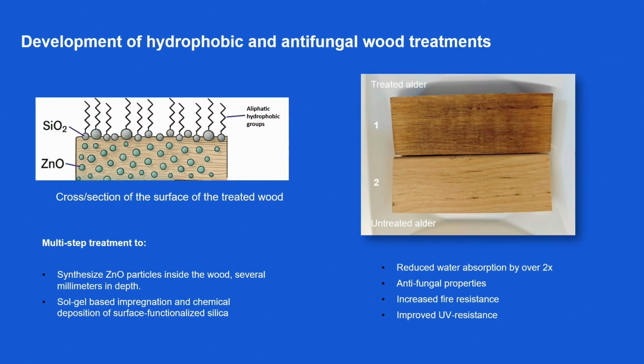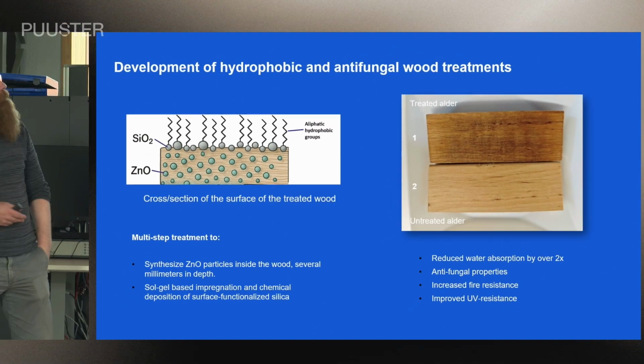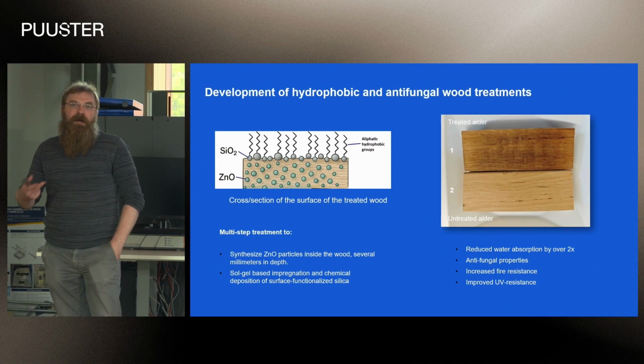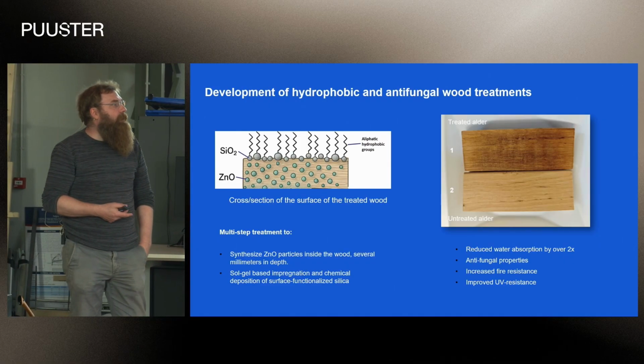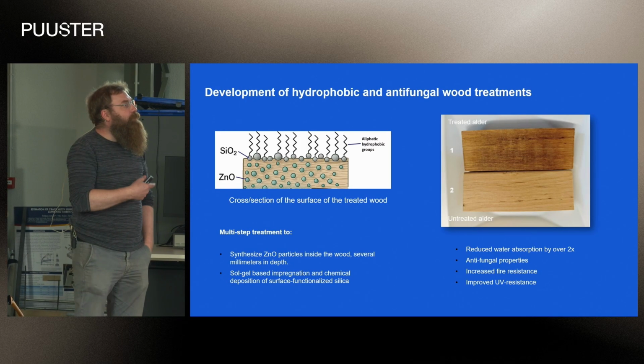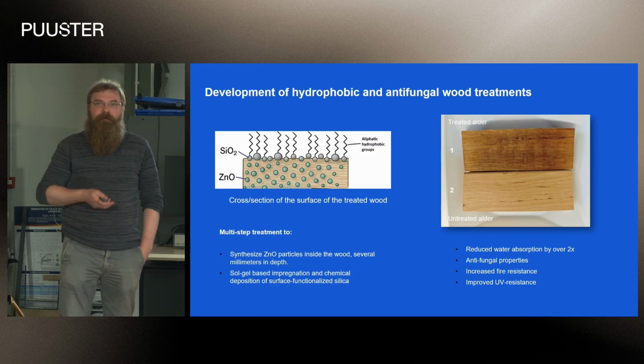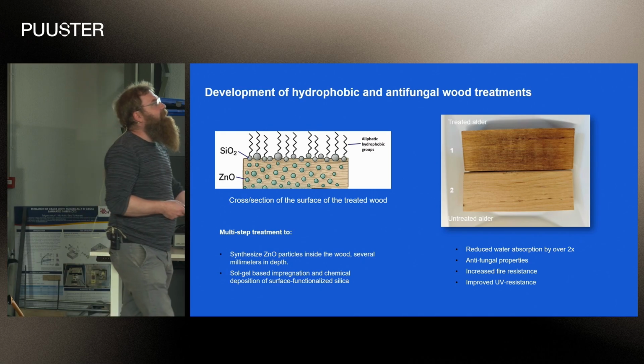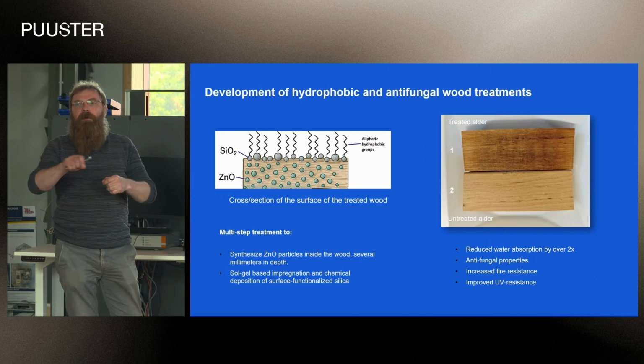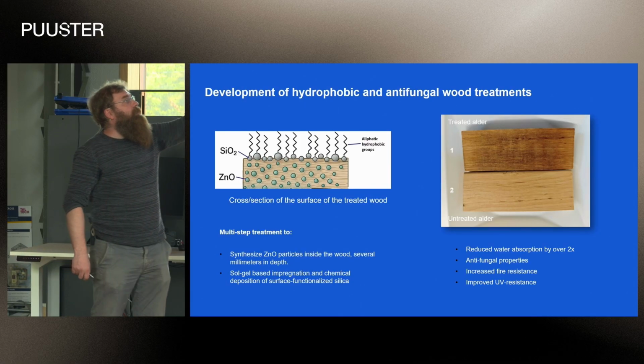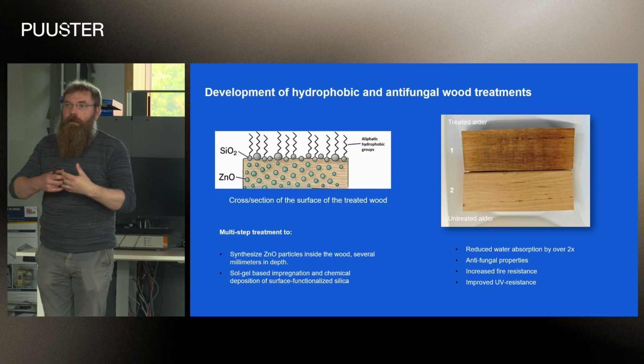Then about this hydrophobic and antifungal treatment that Martin is developing at the moment, we have the samples which is based on alder here. So we have an untreated sample of alder, we have a treated sample of alder, and the novelty is that we want to grow, for example, metal oxides, which, for example, in the zinc oxide case can be antifungal. It also should improve the UV resistance of it, maybe also increase the fire resistance of the material. So the idea is that we are not just coating the sample with zinc oxide material, but we want to grow the zinc oxide inside the wood structure itself.